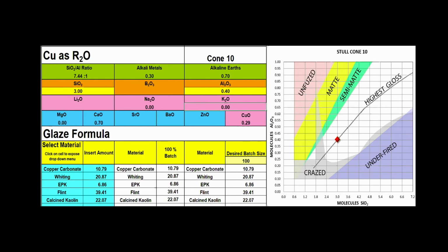So the way we started out was Matthew wrote a new UMF calculator in Excel that accounted for copper as one of the R2O fluxes. And we designed a formula with the least ingredients possible, which were copper as our sole R2O flux, calcium as our RO, flint, and then alumina. In some formulas, we were going to have too much alumina, so we used calcined kaolin to deal with viscosity of the suspensions.